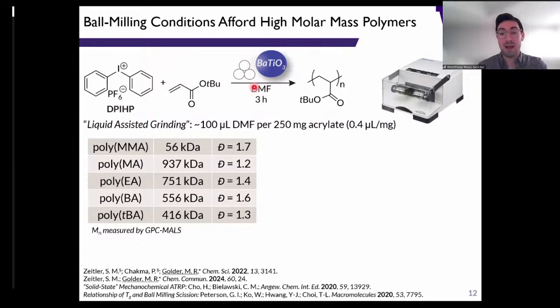I want to point out that we're adding a really, really small amount of solvent here. In this case, dimethylformamide, which is a polar aprotic solvent. We're under liquid-assisted grinding conditions, so we're adding just a few drops of solvent to each reaction mixture. We end up with these really, really high molar masses. This is just uncontrolled free radical polymerization.